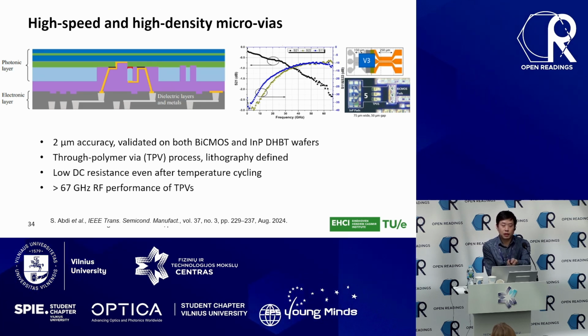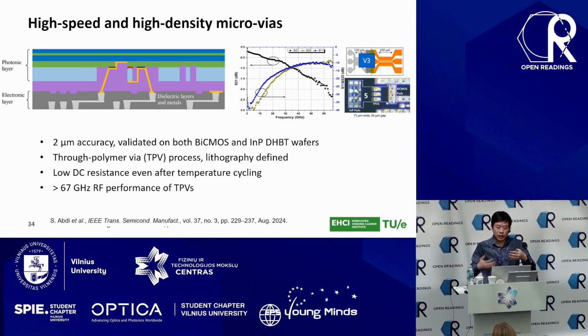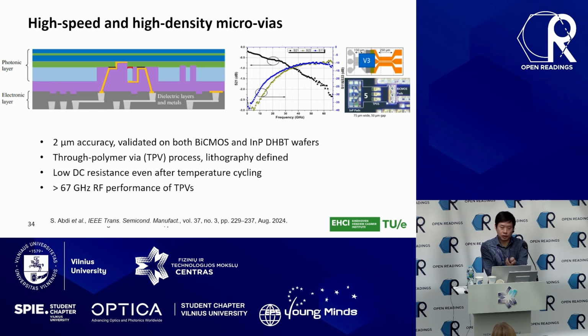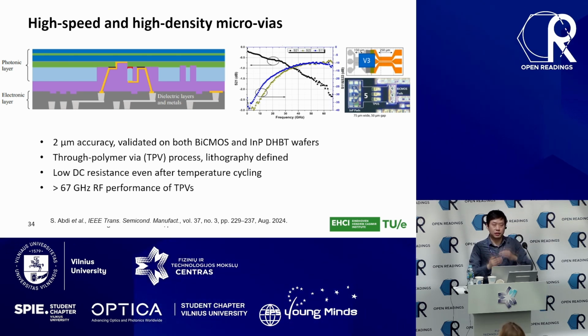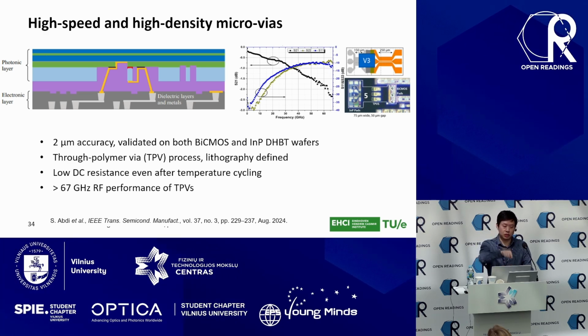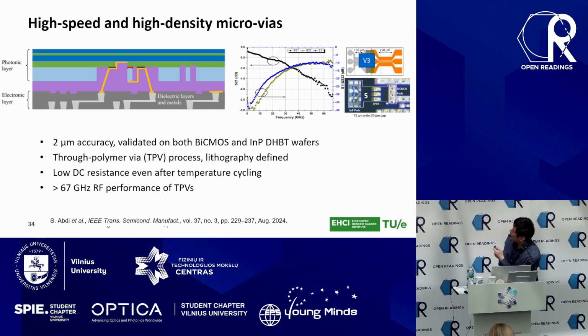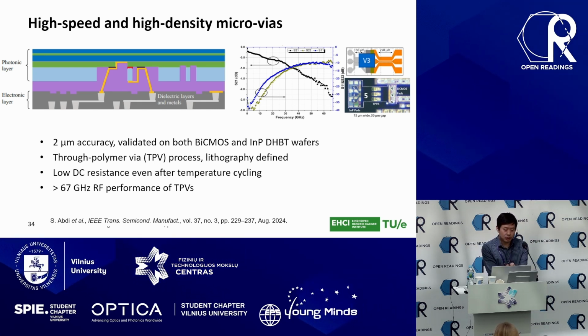On the top right, you see a typical test structure: a transmission line on the CMOS, and the transmission line from the photonic side, and in between, in the blue square, is the via that connects the two. And note that they are not in the same plane. They are 3D. They have an offset in 3D. So this wire is going downwards into this screen. We characterized these test structures. Very good electrical performance, no degradation after temperature cycling, and these vias can support more than 67 gigahertz RF transmission, with negligible loss. So this is way beyond the state of the art in chip assembly technology.